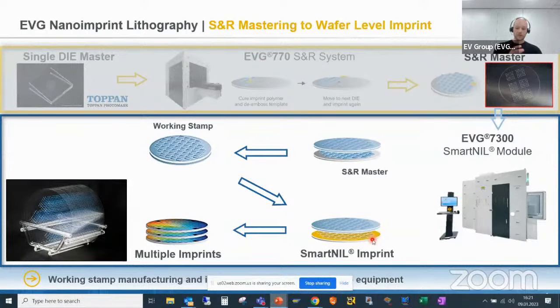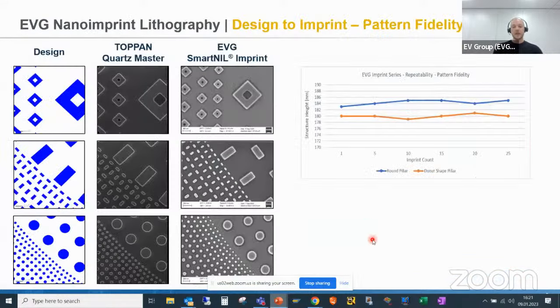For the imprint fabrication, it's of course important that the very first imprint has the same quality as the 25th or the 50th imprint, because otherwise you will have different optical performances. When we check, for example, this batch of 25 wafers, which we have imprinted with one working stamp, you see the pattern fidelity is really stable. We have checked different pillar geometries, for example fully round pillars, but we also checked what we call donut shaped. And the pattern height is really stable across these imprints.